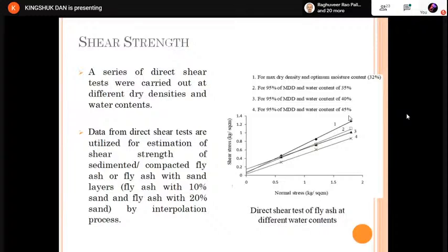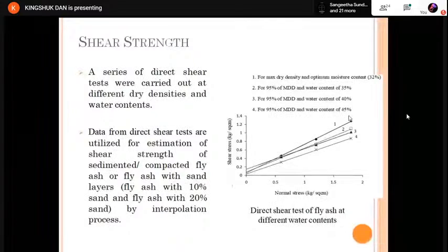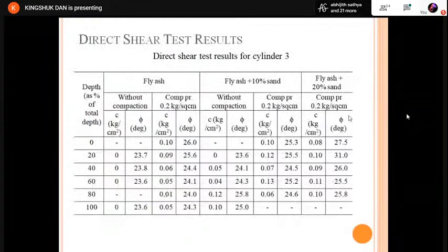Now for strength, we have done shear strength tests with different maximum density and different water content. We get c and phi values, and from these values we can estimate the shear strength of sedimented fly ash and fly ash mixed with sand by interpolation, and these results are shown here. You can see from the data, this is cylinder 3 data, that with compaction the c and phi values, that means the strength parameters, are increased, that means the strength behavior is enhanced. Whereas when we mix with sand, similar kinds of results are available.